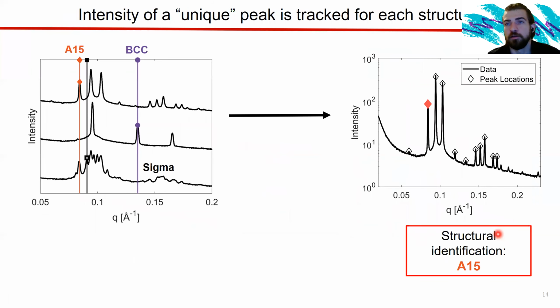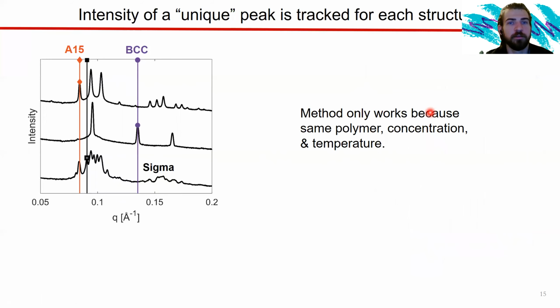So if we're studying these phases over time, we want to know the relative amounts of them. And for this system, there are 3 different peaks: a peak here in BCC doesn't overlap with the other phases. We have an A15 peak that doesn't overlap, and a sigma phase peak that doesn't overlap. So I'm going to say each of these are unique peaks to each of these, and we're going to track the intensity of our unique peak over time and get a metric of formation that way.